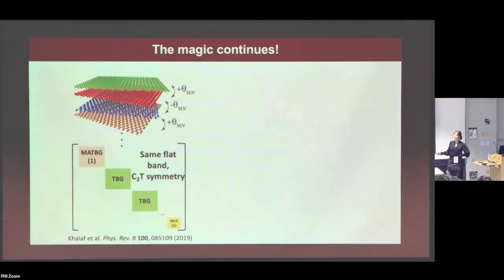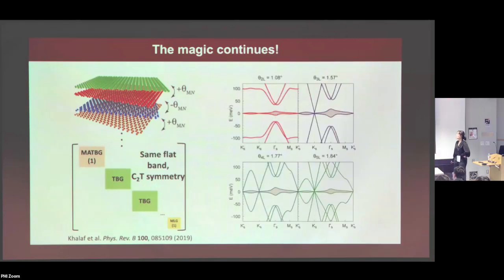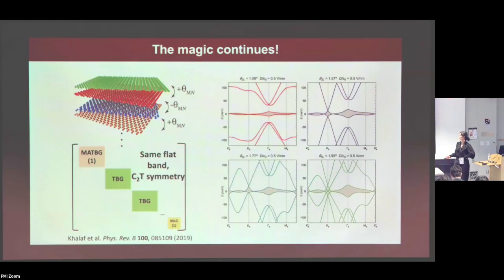And this is actually a very good system for answering our original questions that we started with, because we always have this exact same band with the same C2T symmetry, but then you have these other bands coexisting. So you can see the band structure for 2, 3, 4, 5 layers, they all share this flat band with some other bands coexisting for the other number of layers. You can also do the displacement field control.